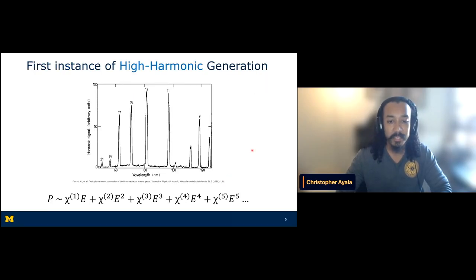It isn't until about 20 or 30 years later that the first instance of high harmonic generation is observed. And the main difference that you'll note is that after the ninth harmonic, instead of that decreasing efficiency that I had just mentioned, there's actually a plateau and then it rises again, and we see another increase in harmonic order. This actually shows that we are now in the non-perturbative regime and must now consider those higher order terms to take into account.